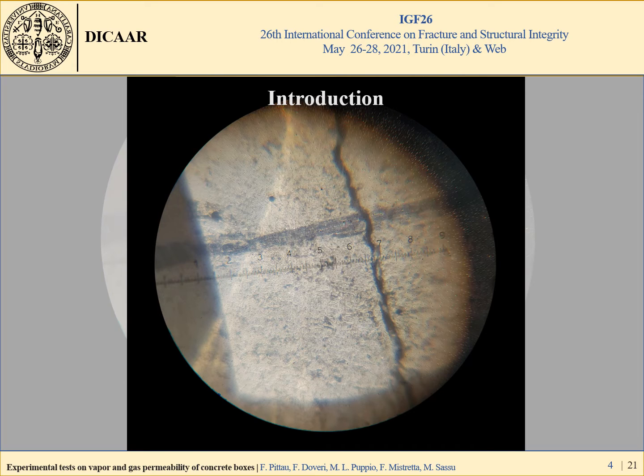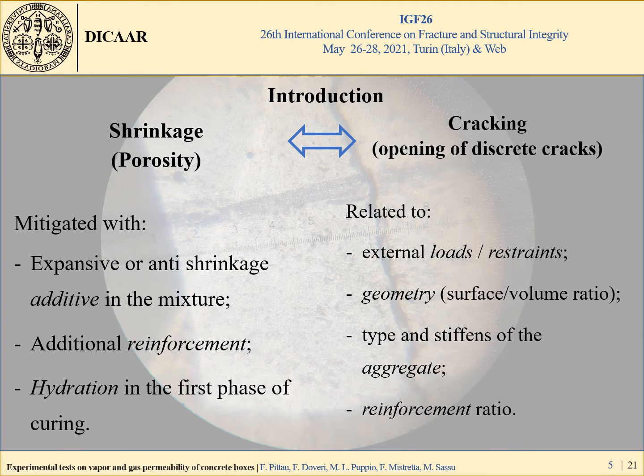This macro shows a typical measurement of the width of a crack with a micrometer. The crack is in fact the primary path of external agents that produce degradation of concrete and reinforcement and undermine the durability of existing structures. Cracking is implicitly admitted all over the world in the design of reinforced concrete structures. The hypotheses of structural design are explicitly based on cracking formation.